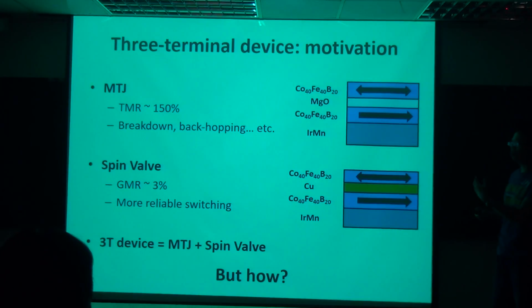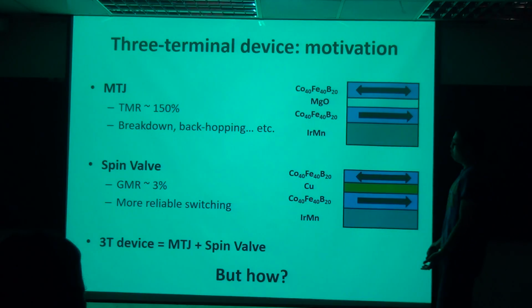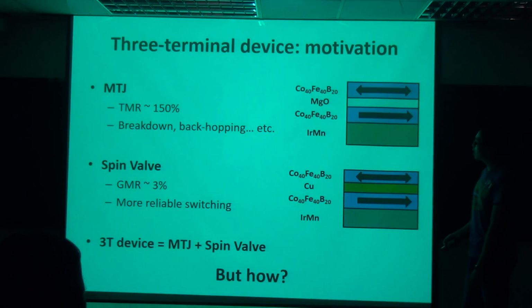Or because you keep writing all the time, and the sample got heated up, and due to the heating, the magnetization starts to become unstable. So once you switch it to another direction, it will switch back. So it causes an error in switching. That's what we call backhopping, and that's what we don't want in a real device.